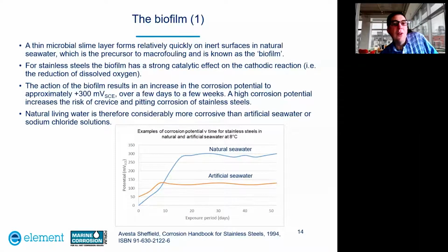So I just want to now talk about the biofilm. So a thin microbial slime layer forms relatively quickly on inert surfaces of metals in natural seawater, which is a precursor to macrofouling and is known as a biofilm. So for stainless steels, the biofilm has a strong catalytic effect on the cathodic reaction, which is a reduction of dissolved oxygen. So the action of the biofilm results in an increase in the corrosion potential to approximately 300 millivolts over a few days to a few weeks. A high corrosion potential increases the risk of crevice and pitting corrosion of stainless steels.